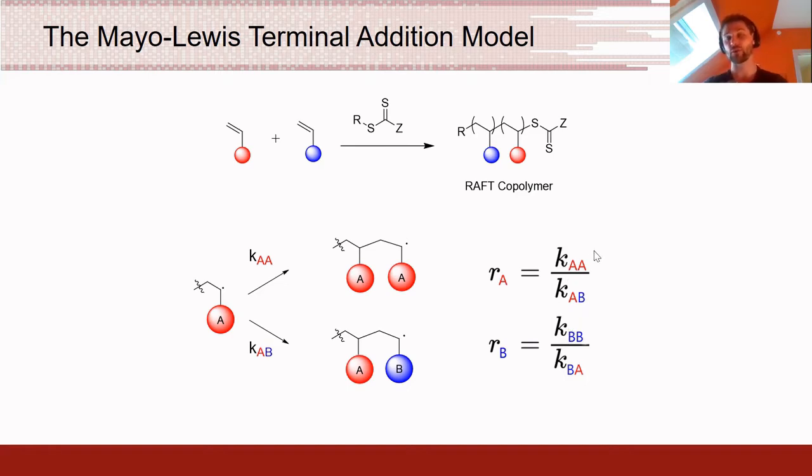If there's no difference between adding on to monomer A versus monomer B, then it will end up being random. Or if it has a higher rate of adding on to itself, then you'll end up with a somewhat blocky copolymer. But this is fairly simple math, and it has been known since, I think, the 60s. And it is very simple to computationally implement. And I wanted to use this tool to pick my initial conditions for my copolymerizations to try to hit some specific designs of copolymers between styrene and maleic acid.